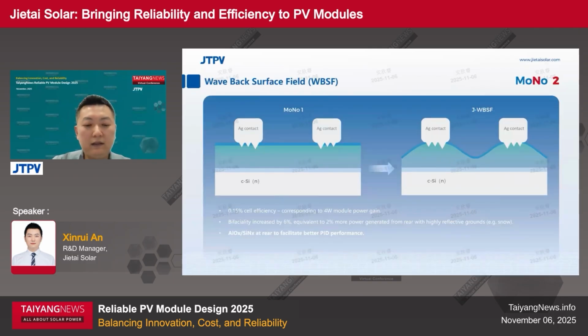And for our second generation Mono 2 cells, the wave back surface field not only increases the cell efficiency by 0.15%, it also increases the bifaciality up to 6%. And with highly reflective grounds, they can contribute about 2% extra power generation. And in terms of reliability, the use of aluminum oxide and silicon nitride stack at the rear means better PID responses.